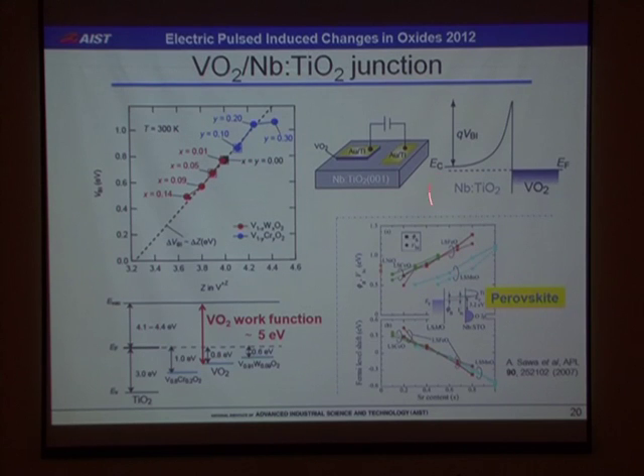So this is a picture of the band diagram. So the depletion layer was only observed in the TiO2 side. And here, the built-in potential is plotted as a function of the nominal valence state of vanadium. And this dashed line satisfies this relationship. And this is consistent with the perovskite report, the transition metal perovskite structure, qualitatively and quantitatively. And deducing from this data, we can make this kind of band diagram.